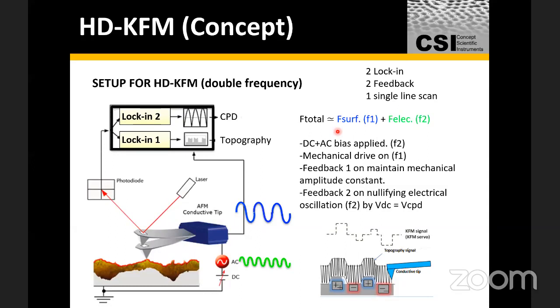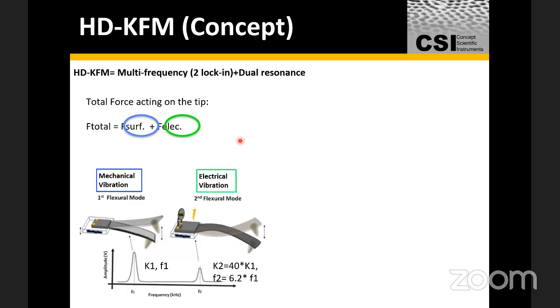And that's what I'm illustrating here: the surface measurement related to the topography is measured in this part of the loop, whereas the electrical response is measured in this part of the loop. Each has its own lock-in amplifier to bring out the actual data, filtered from the instrumentation itself. And as it follows, from the surface, what you get is a mechanical vibration. That is, the surface physically results in a mechanical deflection of the cantilever. Whereas when you're making electrical measurements, the deflection of the cantilever is recorded because of some sort of potential difference, and hence what you're seeing is an electrical vibration. So that's nicely decoupled for us: you can measure the mechanical vibration as well as the electrical vibration of the cantilever.